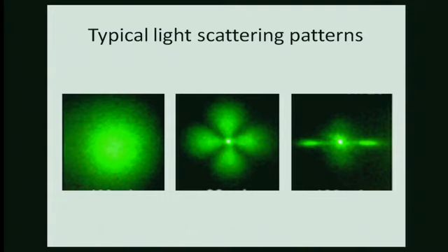For those who are not familiar with scattering, the further the distance from the center of the picture, the smaller is the length scale of variation in our system. If the system is very nicely aligned and has no spatial variations, we would have no scattering at all.